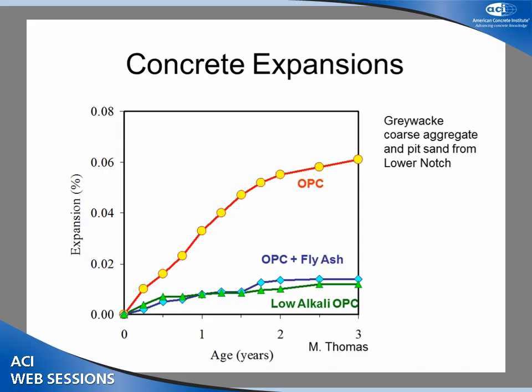And then later on we were able to get some aggregates because they were crushing the rock. There's still aggregate stockpiles of all the different sizes up there. And Mike Thomas remade some concrete prisms, and it shows that with the normal high alkali Portland cements, you would get deleterious expansion. You'd exceed 0.04 a year. And with the same cement and the 25% fly ash or the low alkali cement, you can control that aggregate.